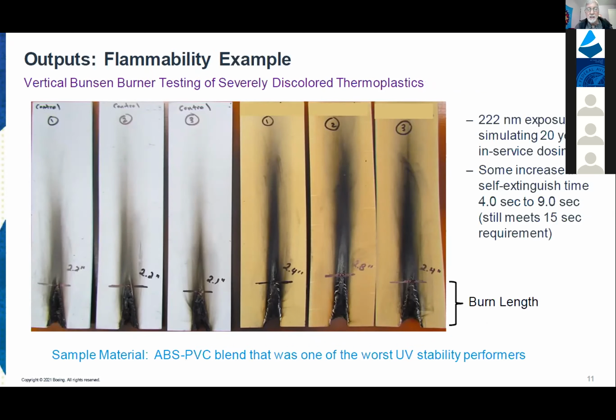What it'll say on the right-hand side is there was a small change in burn length. I think on the right, you're going to see something like 2.6 average, roughly. We did this at 20 years here, and we did it again at 30 years, roughly the same. On the left-hand side, that was the control without any exposure, roughly around 2.2 inches of burn length. The self-extinguishing time did become longer. It was 4.0 seconds on the control, and it was 9 seconds on the one that had been exposed. I think we did have one that was 7 seconds, but I think also on that second test at 30 years, the controls actually self-extinguished almost right away. So there is a little bit of a difference there. Nevertheless, there's still a fair amount of margin between the requirement and how they actually performed.